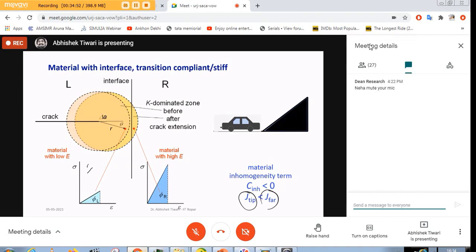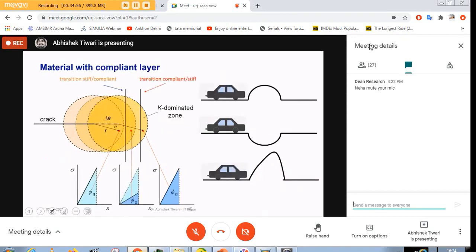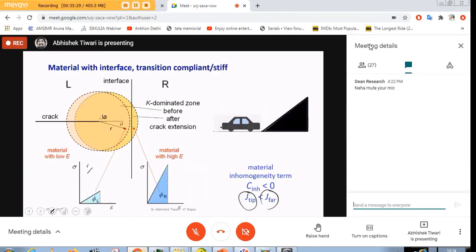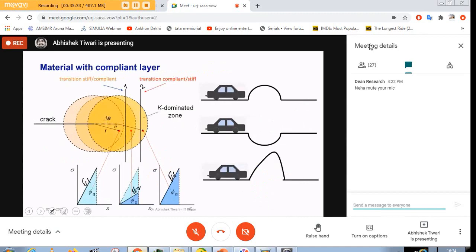If we put a different material as an interlayer in between, then we can break it, as we discussed before. The first interface is a transition from hard to soft, because the elastic modulus is higher here, lower here, and it comes back to the same at the end. At the first interface, the crack is moving from a high stiffness material to a lower stiffness material, and vice versa on the second interface. So what will happen at the first interface? If we look at this, the car will go downwards, and what will happen at the second interface? The car will go uphill. So that will be similar to this situation. And if I put an interlayer for which the elastic modulus is higher than the material I have, then this phenomenon will change and we will see this.